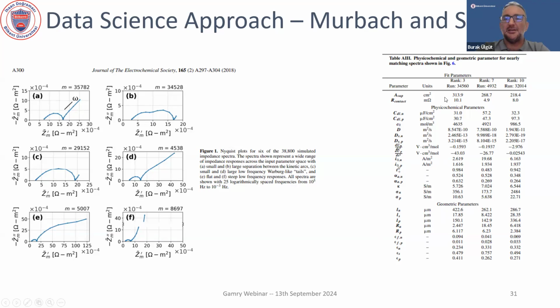And then they said, I can simulate these impedance spectra, and whenever I collect my spectrum, I can match the spectrum with what I've calculated, and voila, I have my parameter set. The problem with this, as the table on the right shows, is it is degenerate. Multiple different parameter sets give rise to the same exact spectrum because, as I said, time constant is our only knob. If I flip the processes of anode and the cathode and give them the opposite time constants, I can get the exact same spectrum.